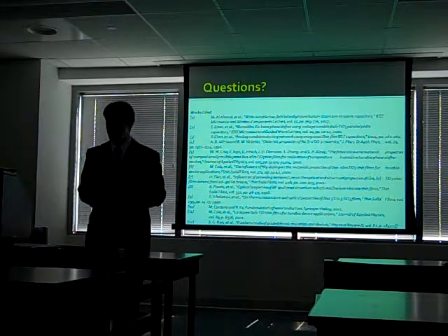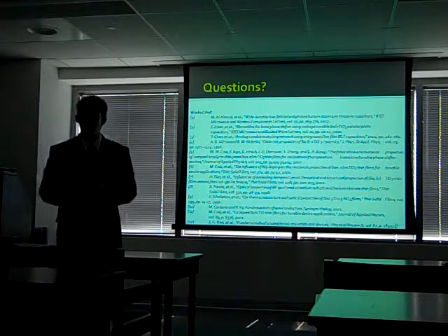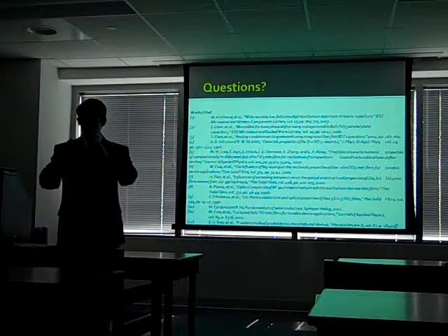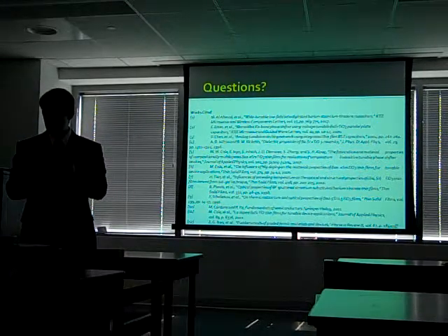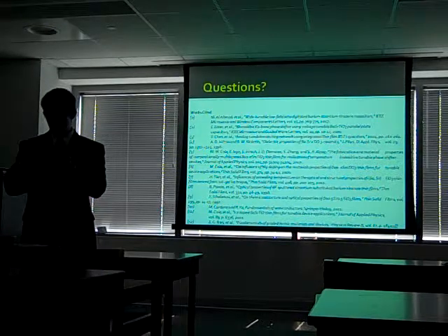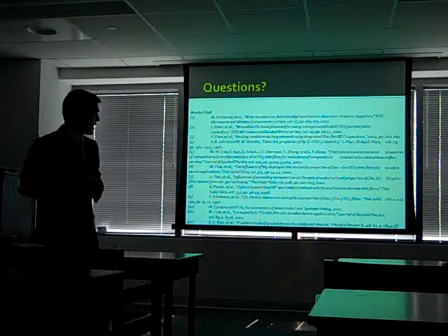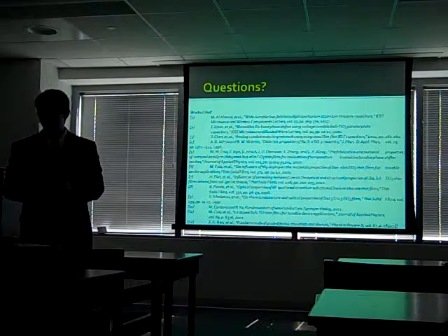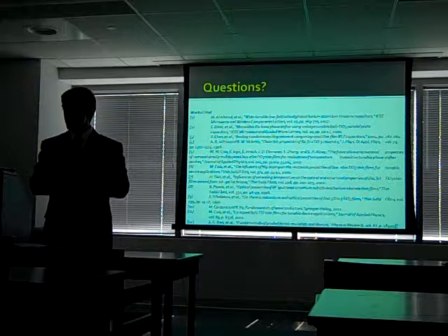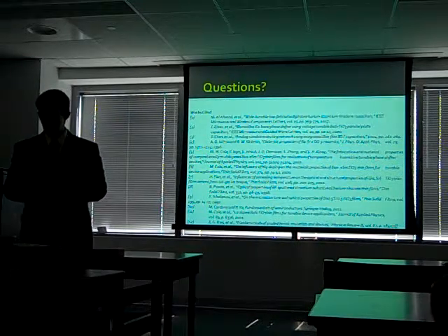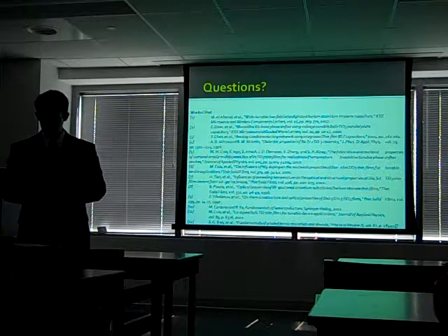Yeah, and that is certainly a concern when you're preparing the samples with the FIB. I know Wanan Chen took his time. It was he and I down in the FIB. Actually, he should take most of the credit for this. But when you use a low enough acceleration or a low enough beam current, you reduce that effect, though invariably it's there. I think also ion milling of the sample would help, to remove any amorphous layers. But as for it sparking diffusion, I suppose that's a possibility. Yeah. Fine. Just want you to know.